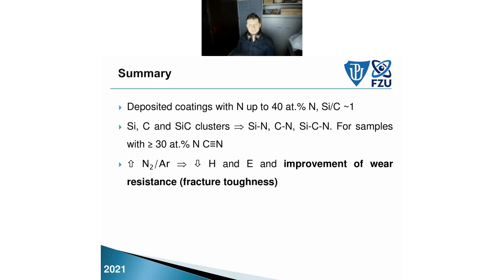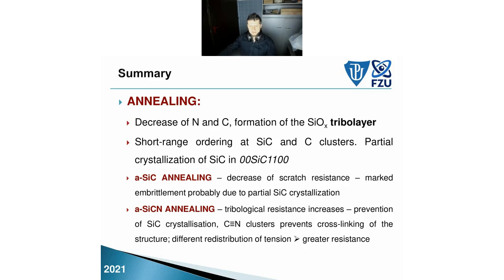So let me summarize the results. We have deposited silicon carbide and silicon carbonitride coatings. We changed the composition of nitrogen, and we can see that nitrogen content decreased the hardness and elastic modulus, but improved the wear resistance and fracture toughness. After annealing, we can see there is a decrease of scratch resistance and marked embrittlement in silicon carbide, probably due to silicon carbide crystallization, because it's always better to keep the amorphous structure.